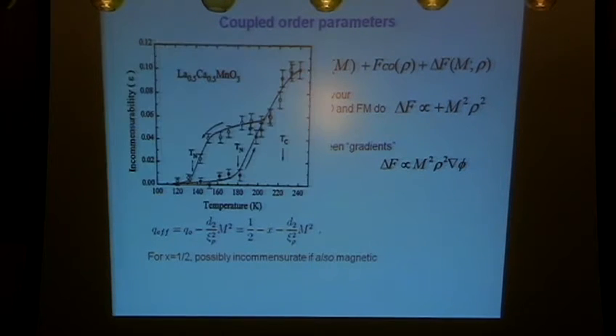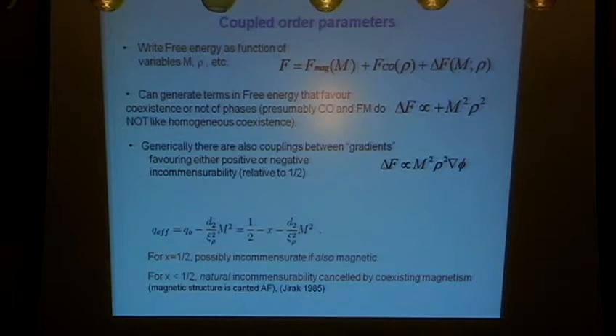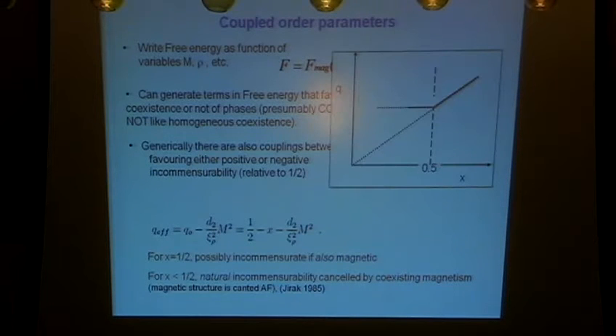Or, and that's basically what you see here, this term actually drives the system away from the commensurate phase to an incommensurate phase that's also magnetic. And the other thing it does is that if I have a doping of less than a half, so that this is positive, and if D2 is positive, this term can cancel that, so I can keep it commensurate, which is what it likes to do, by coexisting magnetism. So that produces that dog's leg.